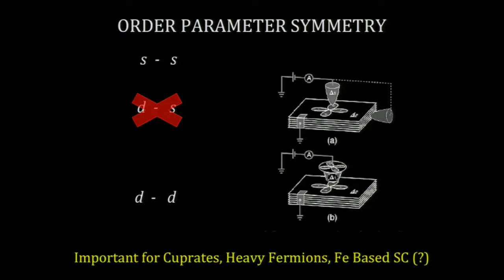And this is particularly important for another reason. One is that if you had taken a lead tip and gone on the cuprates, which are d-wave superconductors, and used an s-wave tip, there's no guarantee that those Cooper pairs from an s-wave tip will tunnel into the Cooper pairs of a d-wave sample. So now we have d-wave in both.